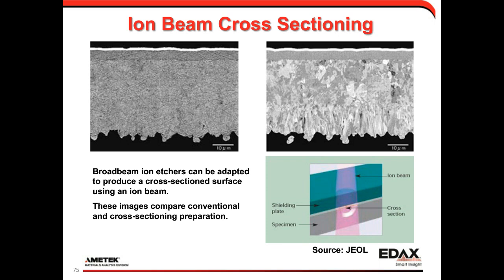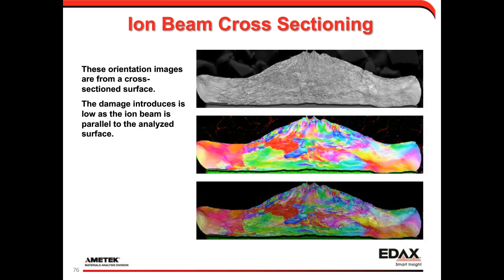So we're not introducing as much direct energy into the crystal lattice of the material we're interested in. So you can see we get nice channeling contrast on the image on the right there, and we also get very nice EBSD results. So this is a result from a gold wire bond sample, and this would be very difficult to prepare for EBSD conventionally. The ion beam cross-sectioning is a very good alternative.